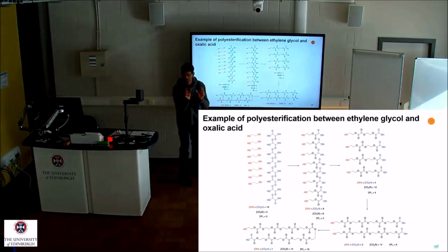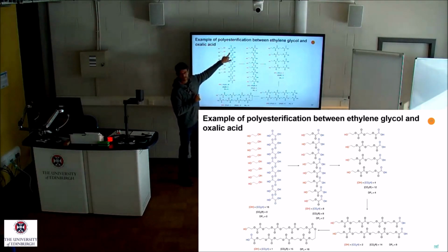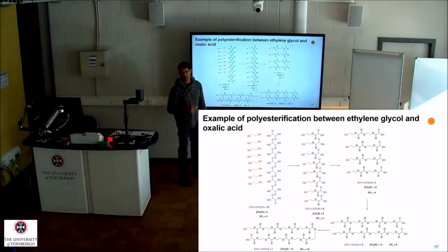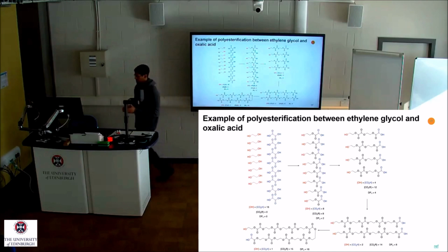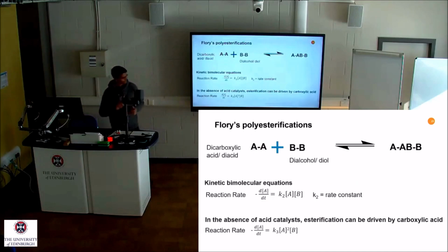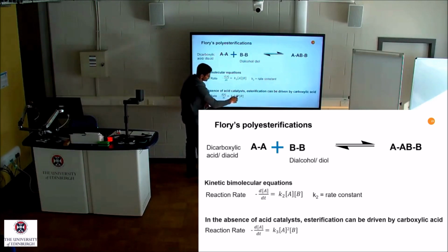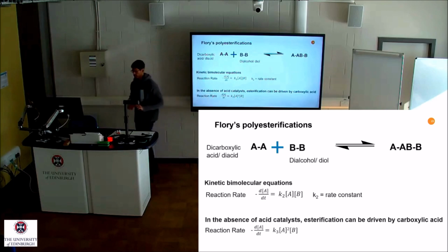So in the actual rate equation, you have 1, 2, and 3 molecules of it. And these two are the same, that's why you put the power 2. And it is also experimentally verified. When you do this reaction without any catalyst, they find that the reaction follows a third order reaction. So 2 plus 1 is a third order reaction. It's experimentally verified, and this is really understandable, right?